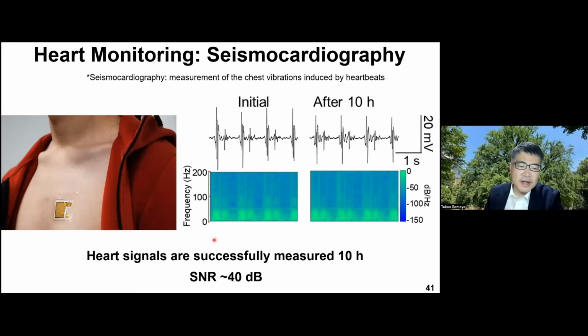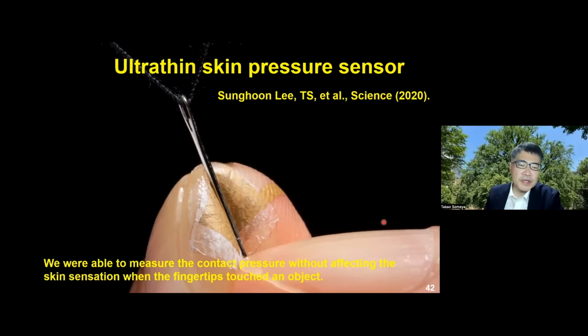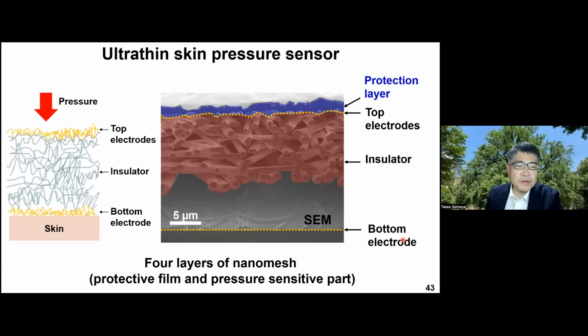The heart signal has been successfully monitored continuously for 10 hours with a high signal to noise ratio of 40 dB. We didn't see any severe degradation of signal quality after continuous monitoring for 10 hours. Another example is on-skin pressure sensors. We are able to measure the contact pressure without affecting the skin sensation when the fingertip touches an object. Our skin sensors are manufactured by laminating 4 nanomesh layers: the bottom nanomesh electrode, nanomesh insulator, top electrode, and the surface is covered by a protection layer.